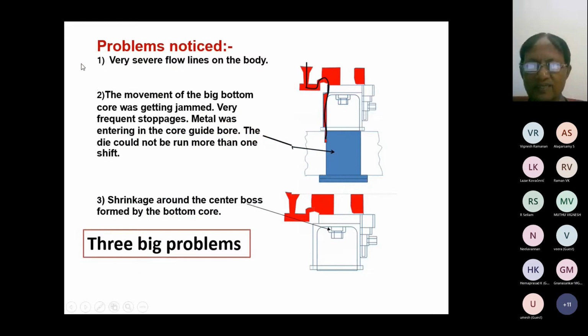But a lot of problems we encountered. There were 3 problems we saw in this attempt. Very severe flow lines, it was accepted by quality on our request. The movement of the big bottom core was getting jammed because when the metal falls to a height of about 150 mm, this 120, another 30, 150 mm, its velocity is very high.